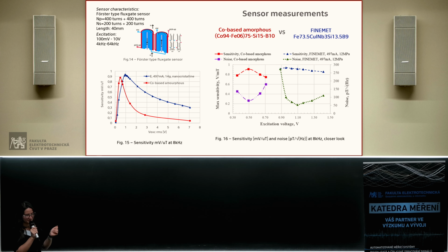And in terms of noise, if you compare noise at the maximum of sensitivity, we apply a certain excitation to get a maximum of sensitivity and measure noise. For amorphous, it will be a bit better. But when we change the excitation, when we increase it, for Finemet it is possible to reach much lower magnetic noise and still get very similar sensitivity to amorphous.